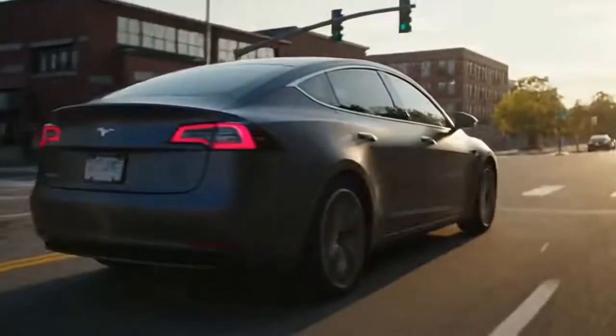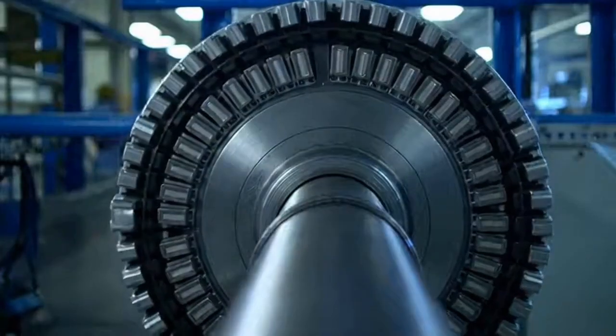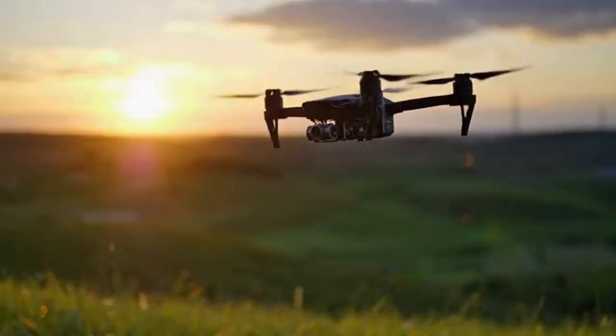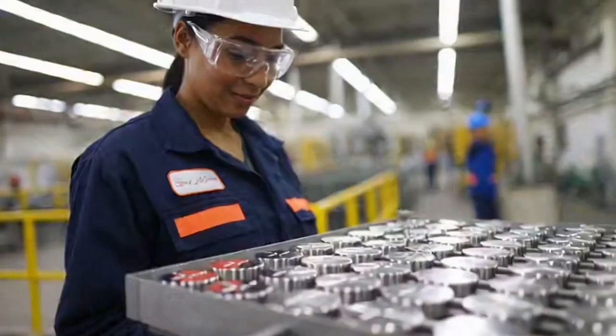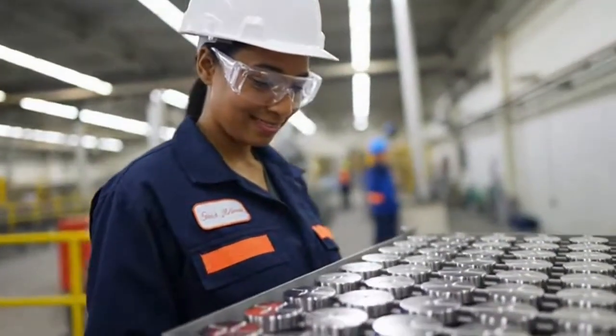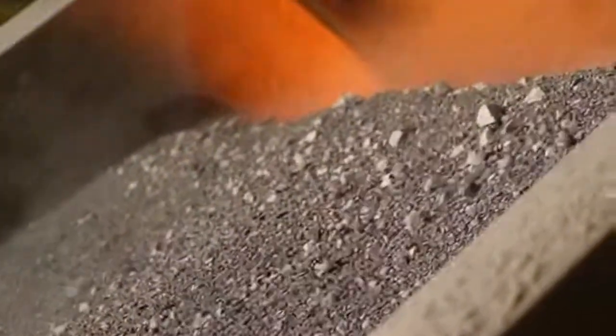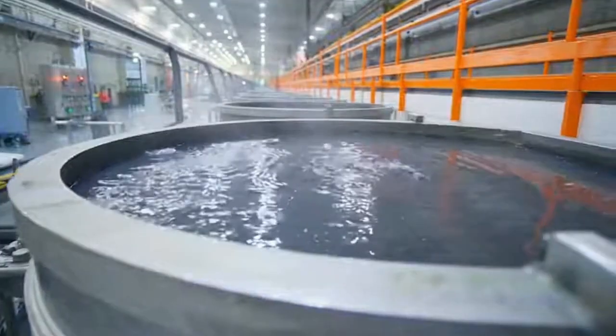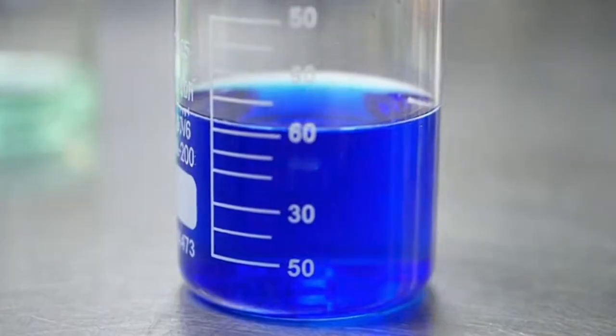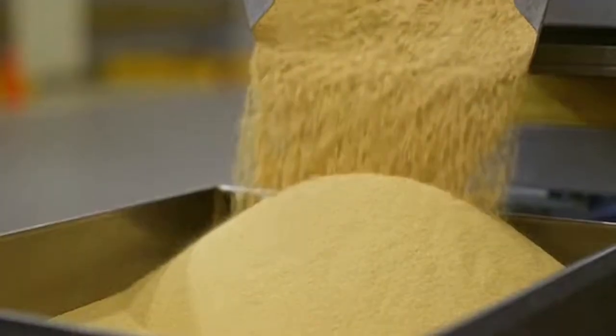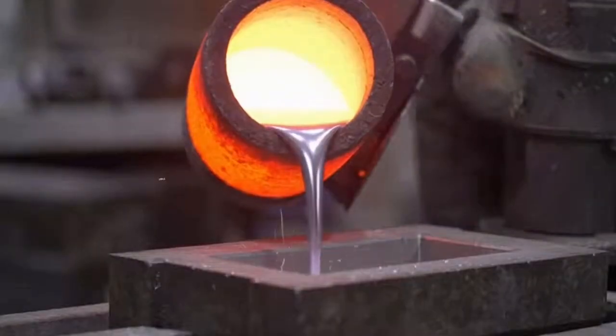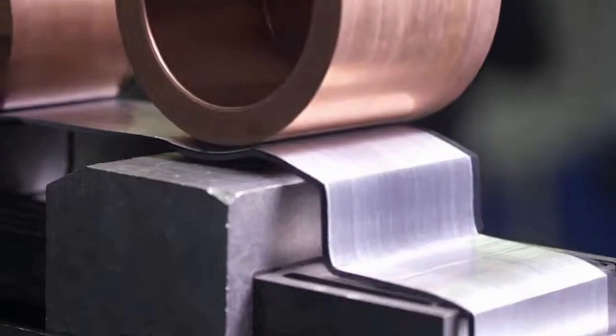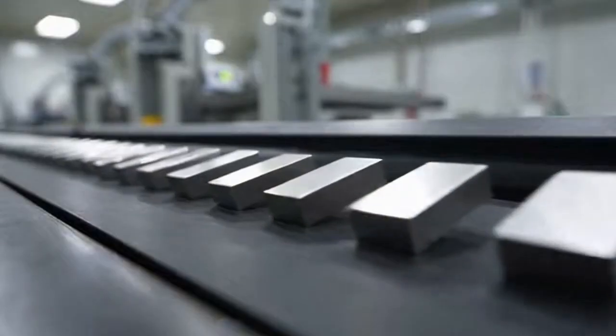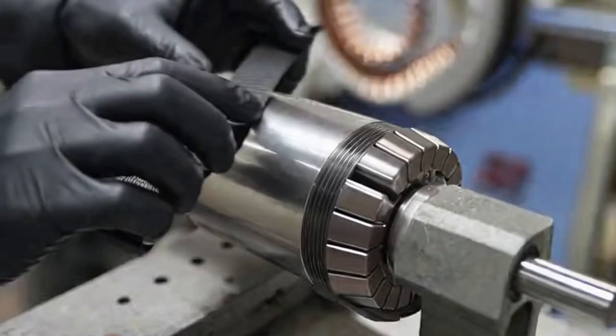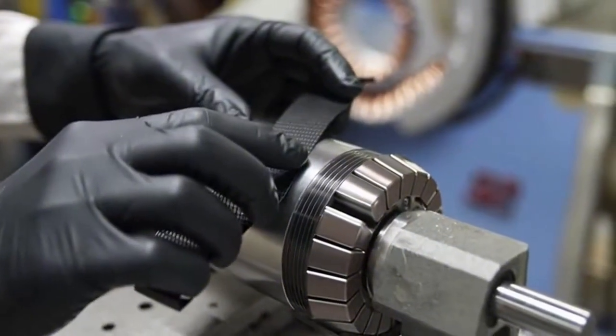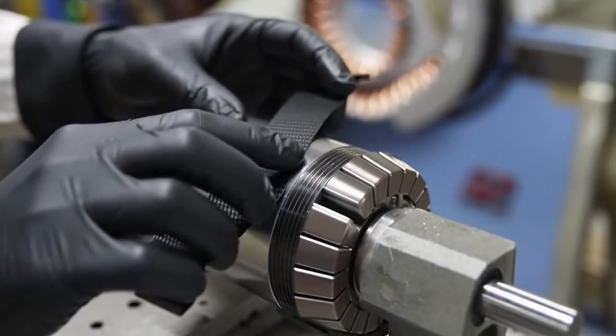Now you have something marketable, let's say a drum of neodymium-praseodymium oxide, often called NdPr oxide for short, which might be 75% neodymium, 25% praseodymium, or some ratio like that depending on the ore. According to the USGS in 2025, that separation step, getting to individual oxides, is still the most tightly concentrated choke point in the global supply chain. Few places can do it at the needed scale, which is why a room full of mixer-settlers in China can feel as strategically significant as an oil refinery.